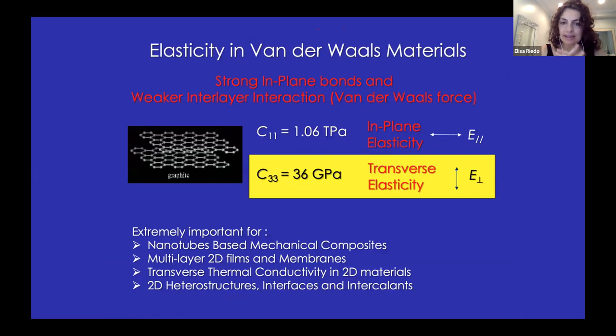So lately, a focus in my lab has been on van der Waals materials. Van der Waals materials like graphene that everybody knows, or transition metal dichalcogenides, boron nitride, are characterized by very strong in-plane bonds. So for example, for graphite, this gives rise to a very high elastic constant C11 in plane, which is about 1 terapascal. On the other hand, on the transverse side, the elasticity is much softer. In fact, the C33 perpendicular to the plane elastic constant is only 36 gigapascal.